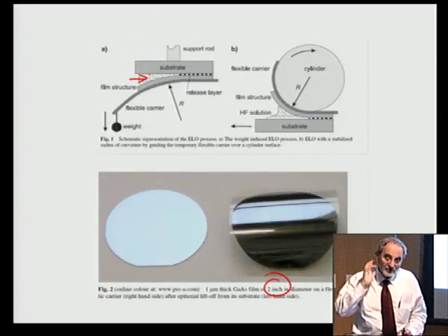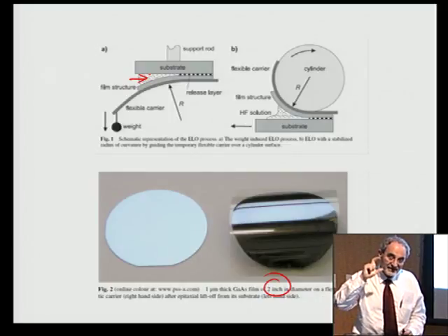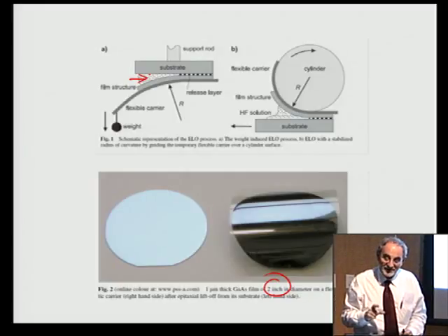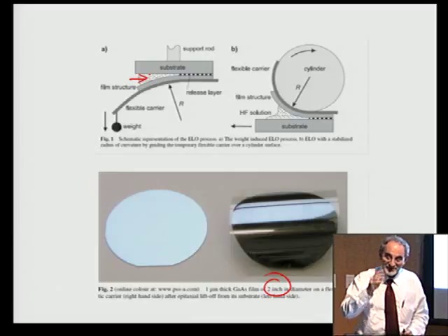There's an amazing coincidence in nature. If you have more than 40% aluminum in the AlGaAs alloy, it is attacked by the acid. If you have less than 40%, it is not attacked. And the selectivity is at least 100 million to 1. And this has not been explained theoretically. We can speculate, but it has never been explained.